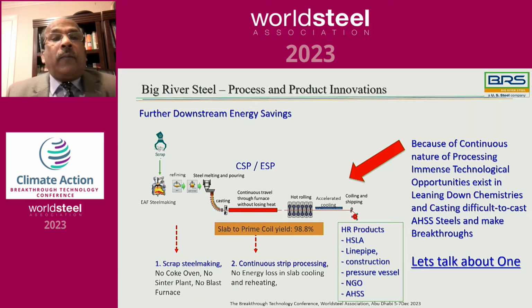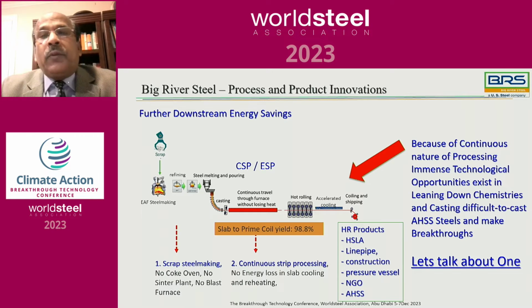So if we see the complete production lineup in Big River Steel, it's a CSP steel production. After the crude steel is made, it goes to the LMF, and from the casting to the hot band coiling, you can see it's a continuous process. So there is no loss of heat in cooling down the slab or reheating back to the soaking temperature. So the slab to prime coil yield is almost 99% here. So the production is very continuous.